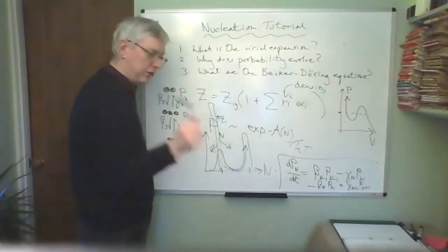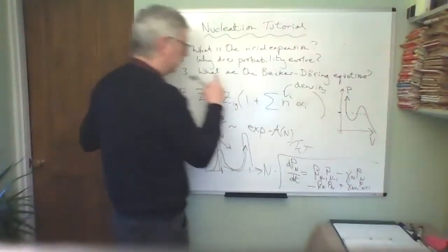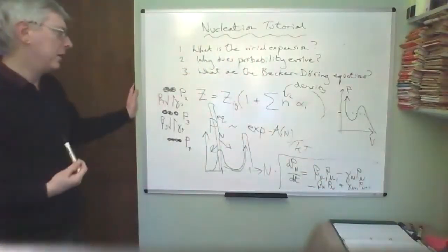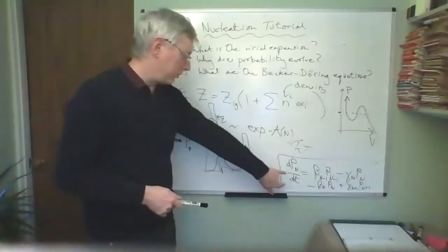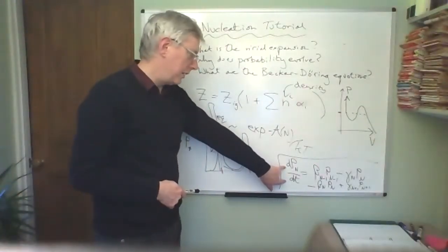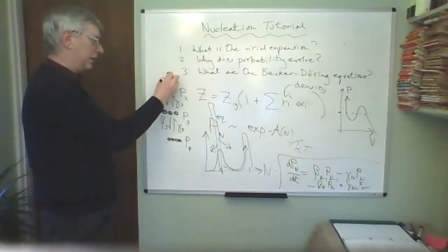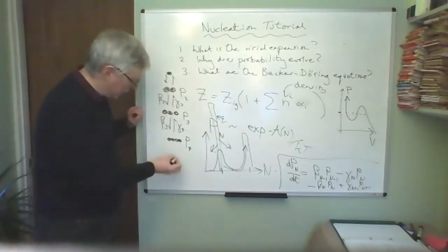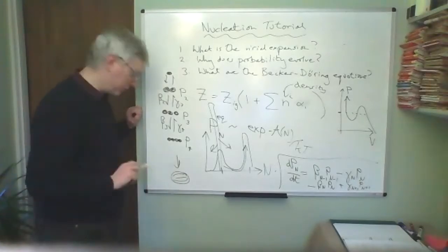We will use them, and that's one of the next questions, to establish a connection between the partition function and these coefficients beta and gamma. That's why that's relevant to nucleation. But we're really interested in solving kinetics of probability, dynamics of probability, and understanding how it is that starting with a monomer, by a growth and decay process, going up and down this scheme, you eventually end up with a big, shiny raindrop that falls out of the sky.